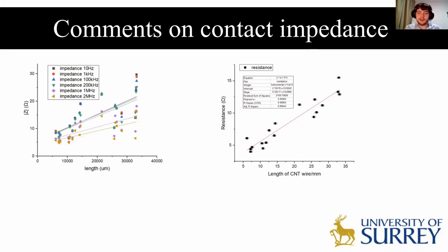The results from earlier also allowed me to reverse the graphing and plot the impedance against the length of the wires at different frequencies. This allowed me to obtain the contact impedance, which would be the intercept of this graph. The effect of frequency on the contact impedance was inconclusive, as although there was a trend that increasing the frequency decreased the contact impedance, the uncertainty in the measurements was greater than the difference, so that alone is not conclusive.